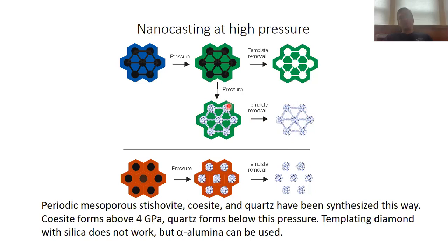the preservation of the mesostructure requires that at least one of the two phases remains chemically inert under the reaction conditions. When you activate them both, then there's a driving force for the mesostructure to disintegrate, okay, because the mesostructure itself is only metastable. Therefore, this step here is thus far a hypothetical step. It has not been experimentally accomplished thus far.